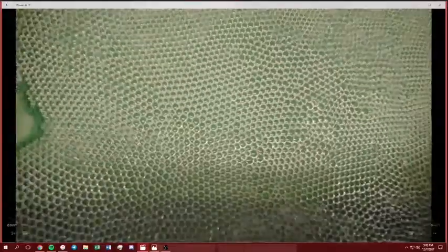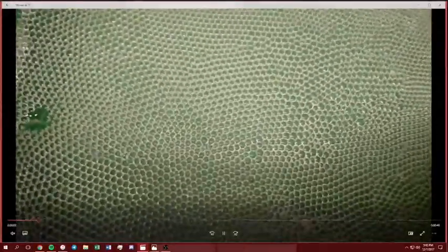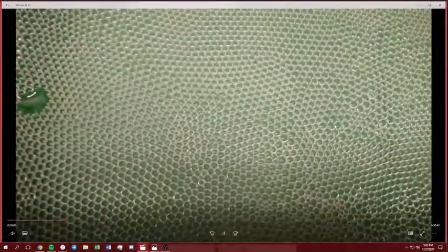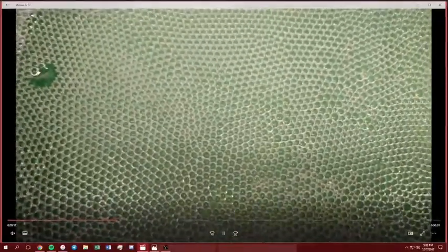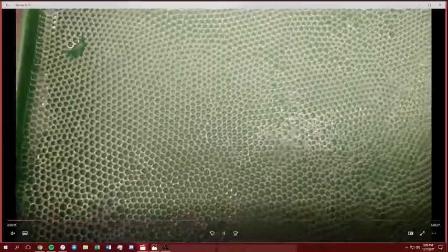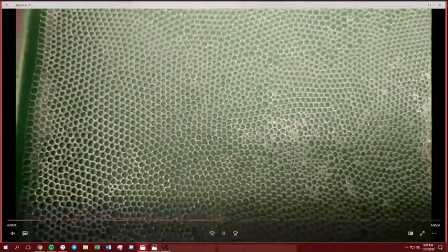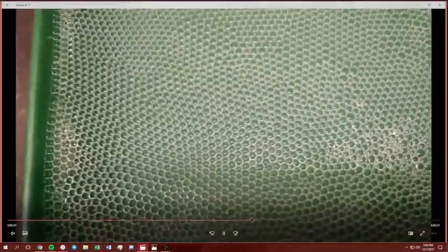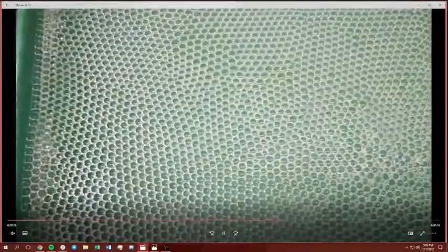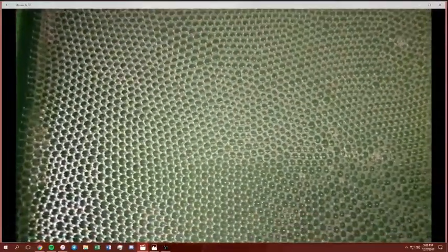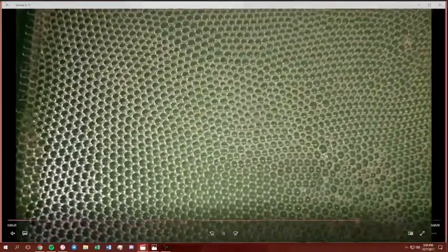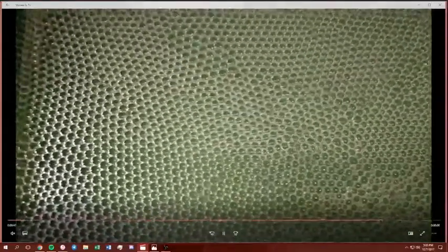Here, for example, is what happens when a bubble raft is put gradually under stress. Now, you can see here that there are grain boundaries, for example, right here. And you can see that as you stress and squish this bubble raft, you will be able to see the dislocations move here. And you can see the way that these grain boundaries right here shift slightly. And so this is how atoms in a crystal react and how the grains in said crystal react, just like this bubble raft, even though they're two completely different substances. And so that's why this is so useful.